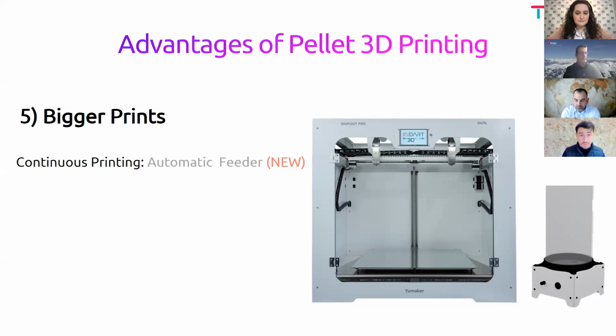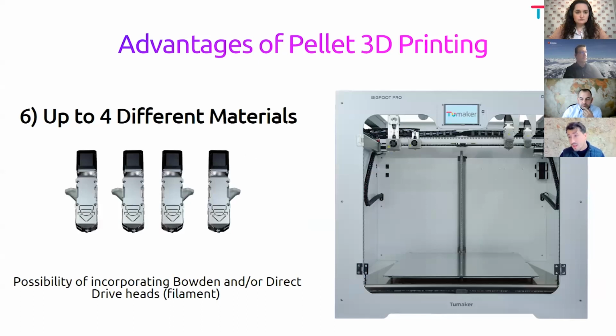Additionally, during filament 3D printing, we always have to make this technical step of changing the coil. This is something that we can avoid using pellet extrusion because we have an automatic feeder that is automatically feeding the pellet extruder. Another one is that we can have multi-material 3D printers. So we can combine up to 4 different independent heads. We can combine pellet extruders also with the incorporation of both bowden and direct drive heads. We allow for the combination of pellet extrusion with filament extrusion.